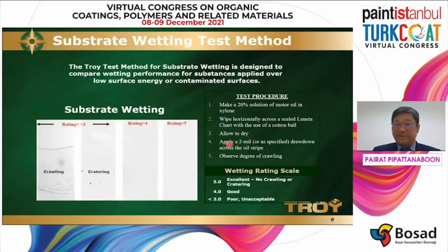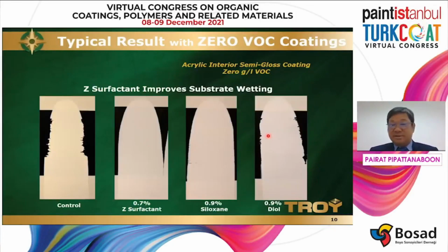Now we're going to run through the substrate wetting test method. We prepare the Leneta chart and apply motor oil mixed with xylene on the Leneta chart, and prepare your coating formulation. Apply 2 mil or 50 micron on the Leneta chart. If you see some cratering or crawling, you rank it from 1 to 3, which is a low rating. If it goes to 4 or 5, it's very good, surface defect free without crawling. This is an example of an acrylic interior semi-gloss coating, 0 VOC. From the 4 formulations, the first one, the control, is without the wetting additive. Please recall that the Leneta chart has motor oil and xylene mix applied on the surface before we apply the coatings. You can see that at only 0.7% with Z surfactant, it helps to control a smooth surface without crawling or cracking on this surface contaminated with oil.